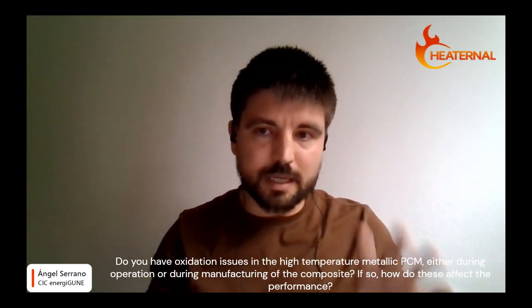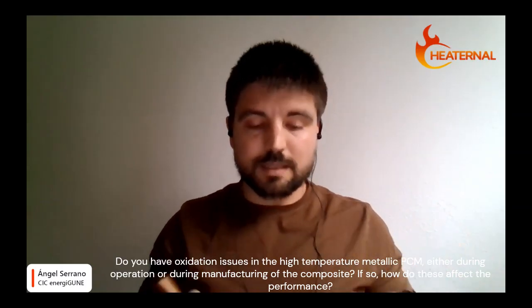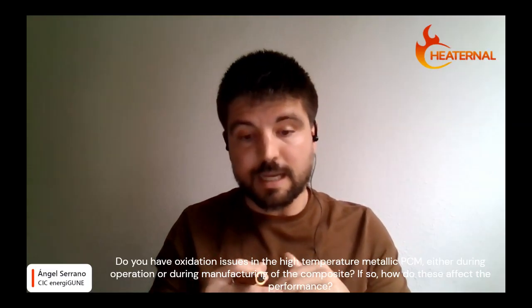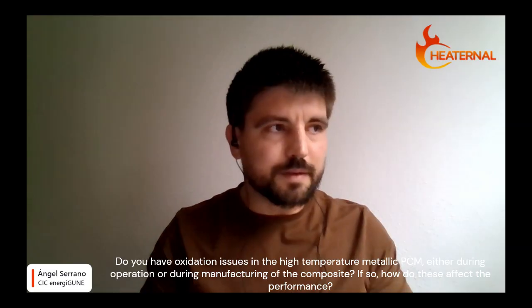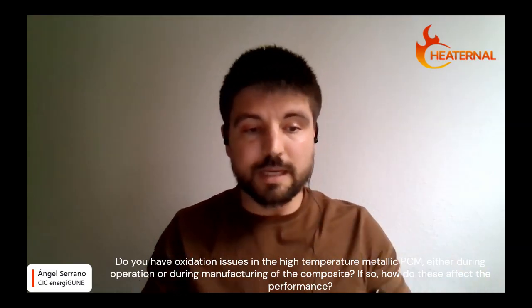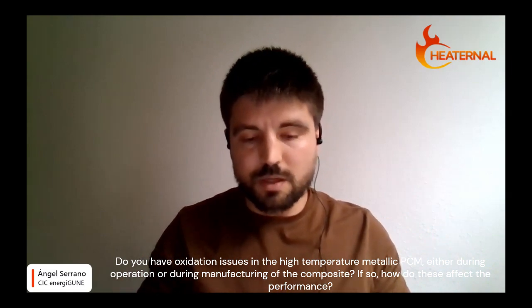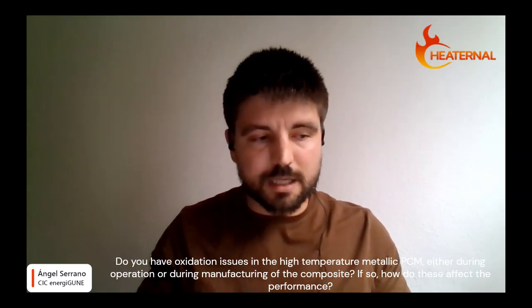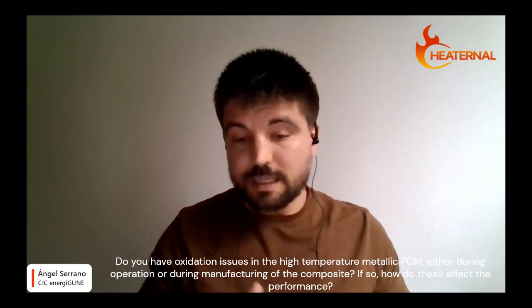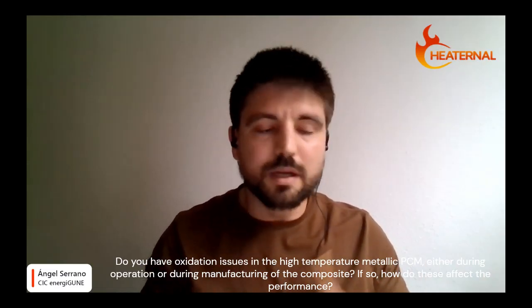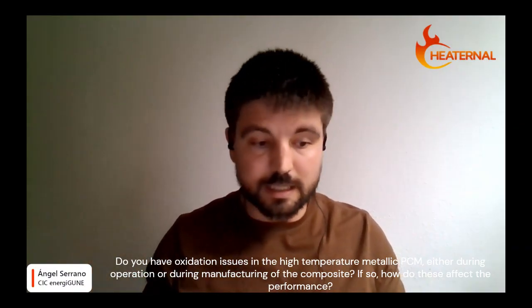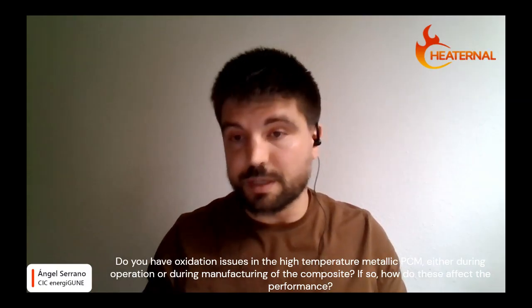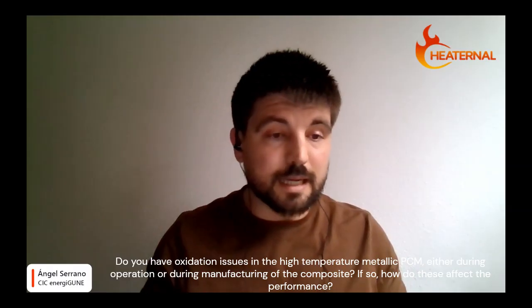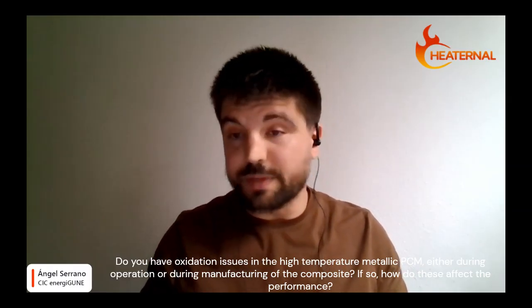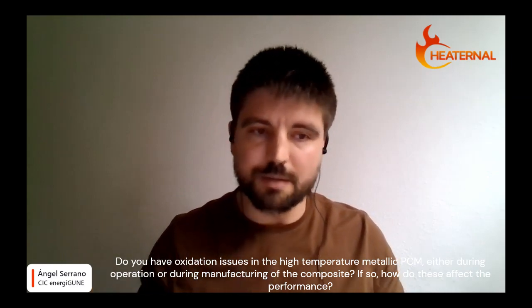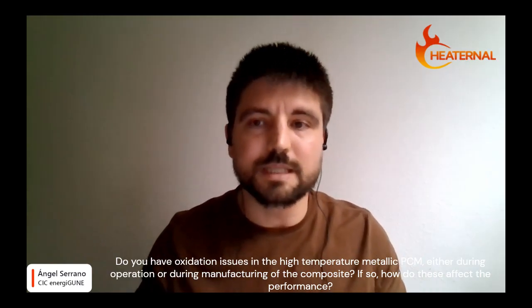So during the design of the PCM, we are taking into account that we are going to have oxidation, but we are trying to obtain a stable oxide layer in the outer part of the metal alloy. Why this is beneficial? Because it avoids the contact of the air with the inner metal alloy and the extension of this oxidation. We have tested over 100 cycles this behavior under air, and we detect this initial drop of the enthalpy, which means that we are starting to have some oxidation, but this stabilizes over the cycle. So in the best scenario, we have detected just a drop of 1% of the initial enthalpy, and in the second or third option that we have, the drop of the enthalpy initially is 15%, but it keeps stable. So yes, we have oxidation, but it is even beneficial in the long term.